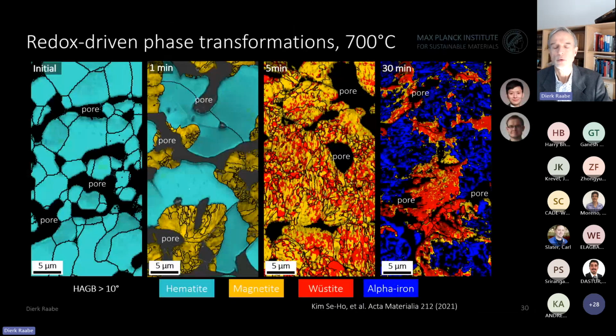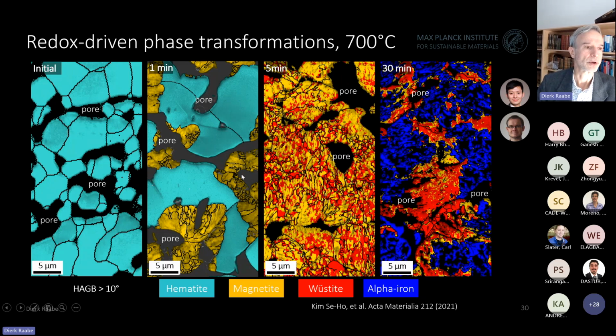Now, when we take an EBSD and phase analysis, as shown here, again at 700 degrees centigrade from the initial towards the near final state after 30 minutes, again at 700 degrees to slow things down a little bit and make them easier observable, you can see that you have an inherited porosity which comes from the sintering process, so offering free reaction surfaces. And these are, of course, also the surfaces, as you can see, where the nucleation of the incommensurate magnetite with its cubic crystal structure takes place. And you have an Avrami-Kolmogorov-like growth of the magnetite into the surrounding hematite grains. So that is kind of understandable.